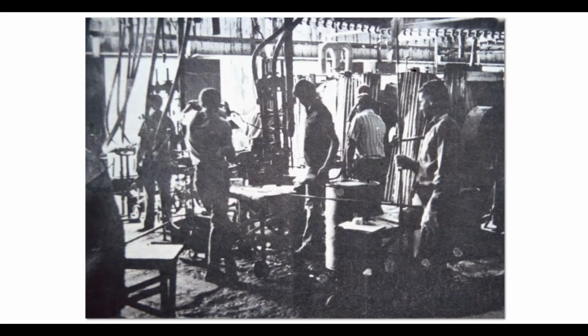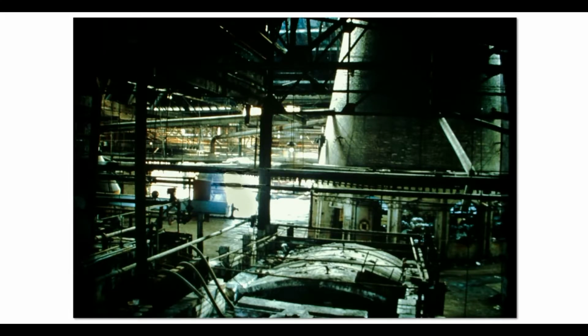This was on the factory floor. That's what it looked like when the guys were working, bringing the glass out of the big old pot furnace and putting it in the molds and pressing it. That is one of the 2 big old pot furnaces right there. In these openings, each one of these openings would have a pot in it, and a lot of gas would come up and be ignited and melt the glass in each of those pots. And normally each pot would have a different kind of glass in it. They weren't making window glass there, they were making tableware, very different colored kind of things, many varieties.